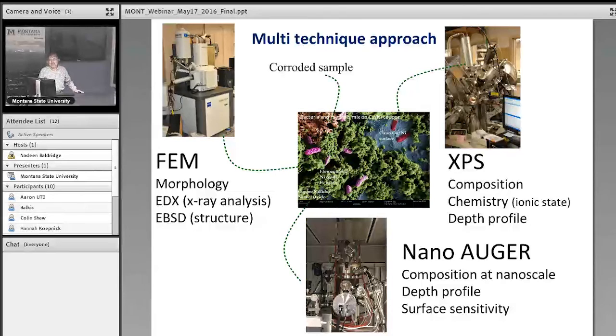They give complementary information. With field emission microscope, I call it FEM, I can see the morphology, I can see the X-ray analysis, I can even get structure analysis using electron backscatter diffraction. With XPS, I can get composition, chemistry, ionic structure: is it copper 2 or copper 0, is it elemental copper or oxidized copper, or the same thing with iron or sulfur, whatever.